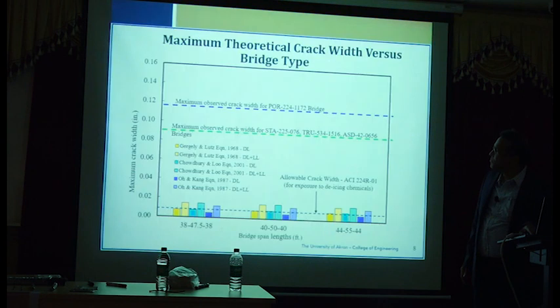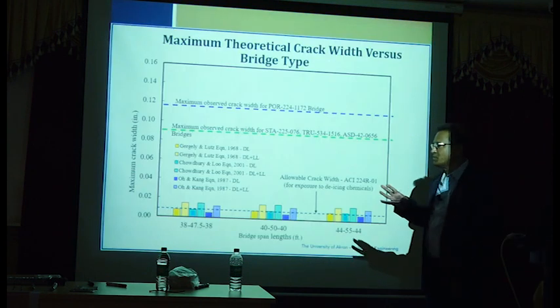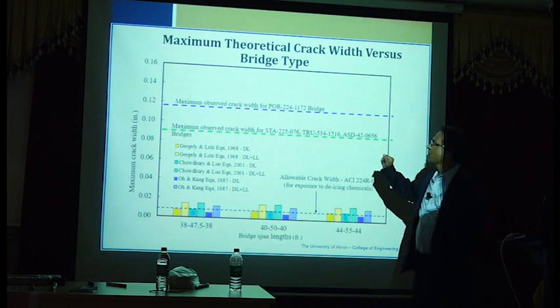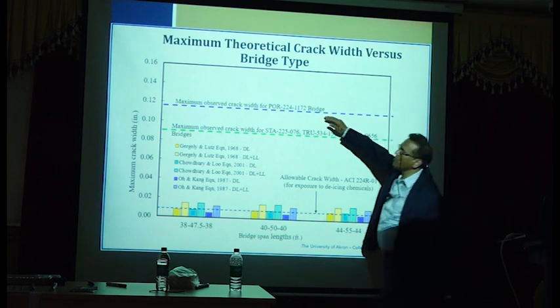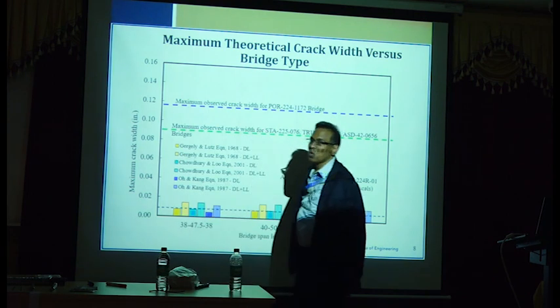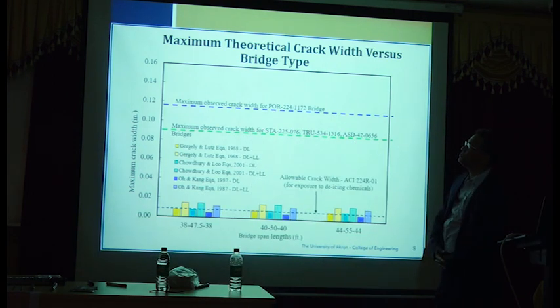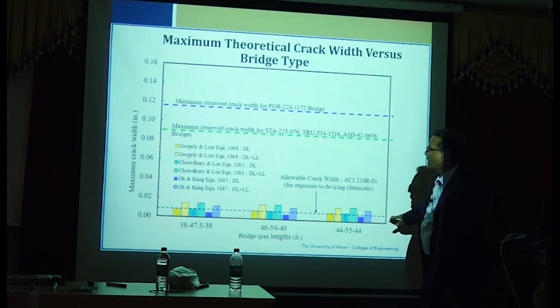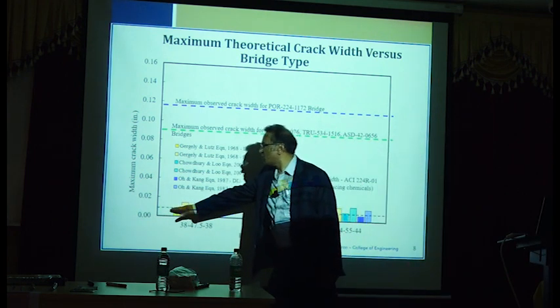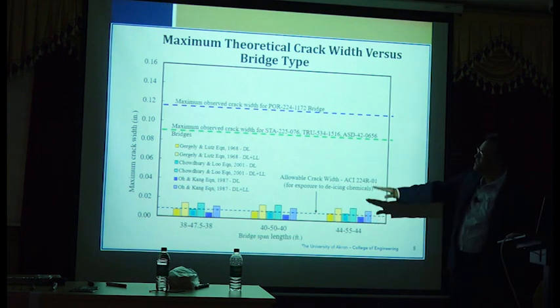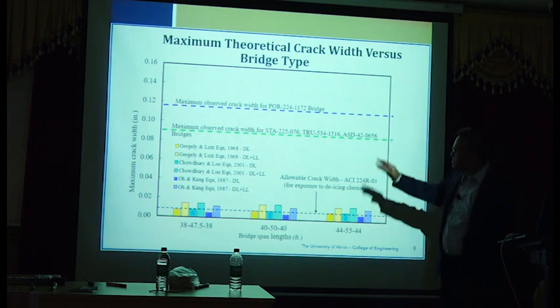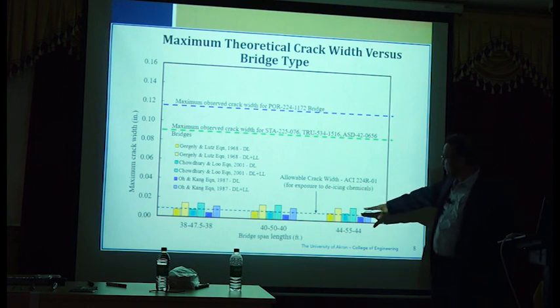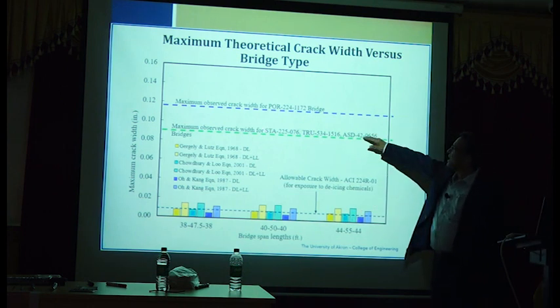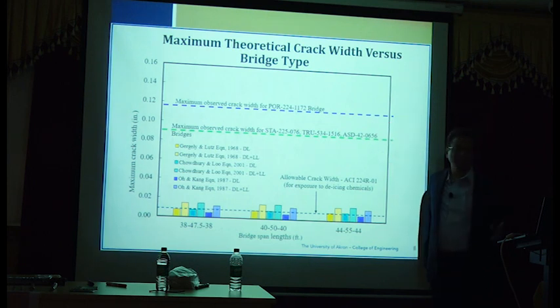So what we did was we looked at a lot of bridges, we did inspections, and we found that the actual crack widths are very, very wide, as much as 1/8 of an inch, like 0.12 inches is a lot, about 3-4 millimeters. And as per ACI, what is allowed is very, very small quantity. So this graphic, without worrying about the numbers, you can see how much difference there is between what is specified in ACI and what we were observing in actual field.